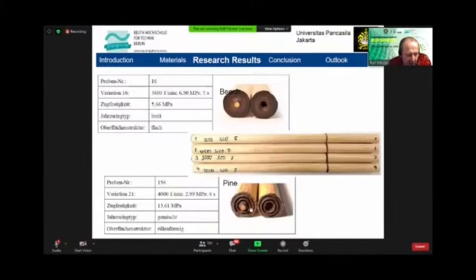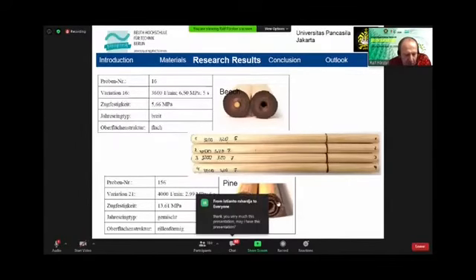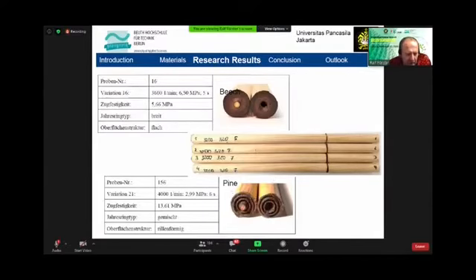Here is the pine, and as you can see, these are the different wood annual rings in the wood structure, and this is also like a gluing connection, like an additional joining connection. And at the pine, in most of all samples, it's a problem, it's the influence of the pine wood. When we have a look at the beech wood, we don't see such behavior. And it's a really different difference of the wood material, and as you can see, the tensile strength of pine is 2 times higher than of beech.